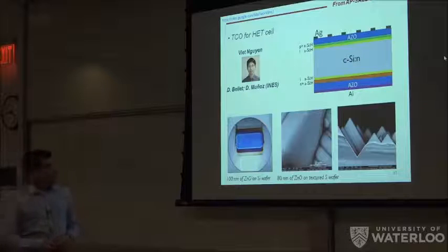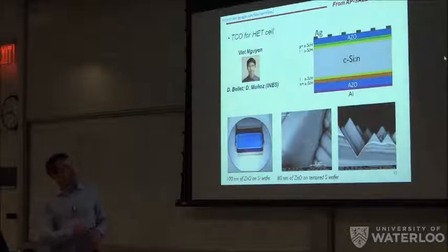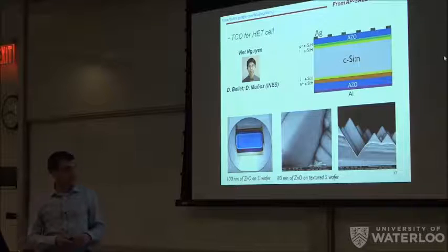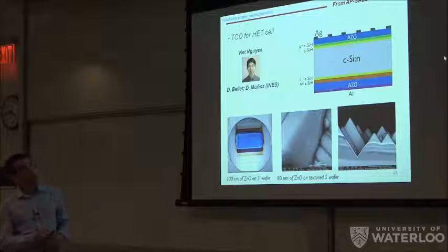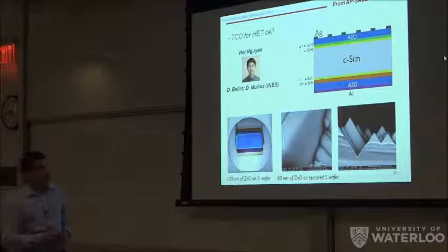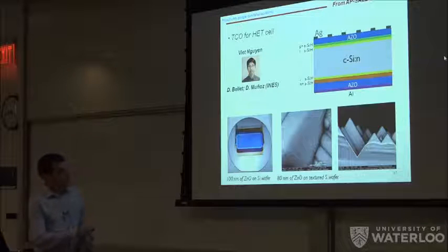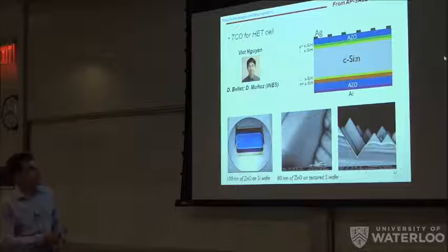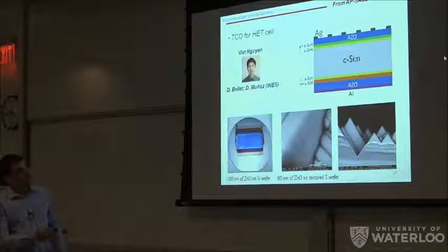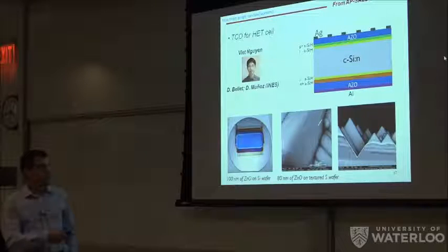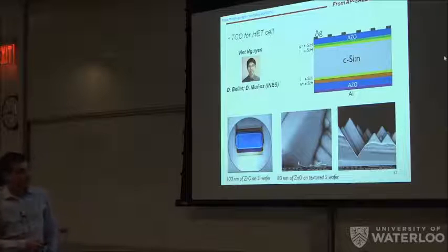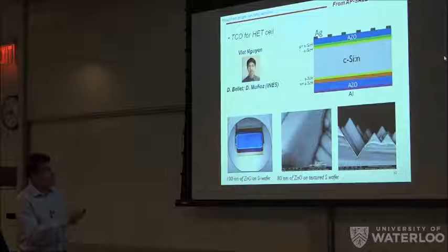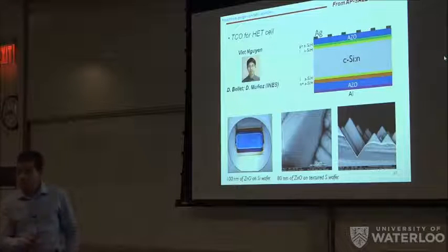enhancement. So we have a project with INES in France, in which we are trying to develop these aluminum doped zinc oxide layers for this type of solar cells. And it's an example of the zinc oxide we are currently optimizing. And again, when we try to deposit it on top of a textured silicon substrate, you can see that it's really conformal and nice. And that's the PhD subject of Viet.